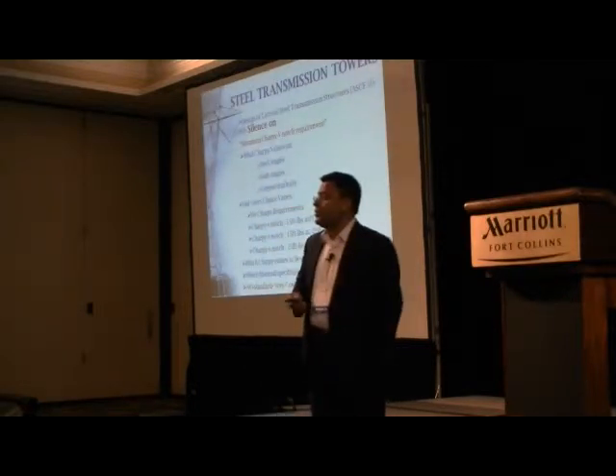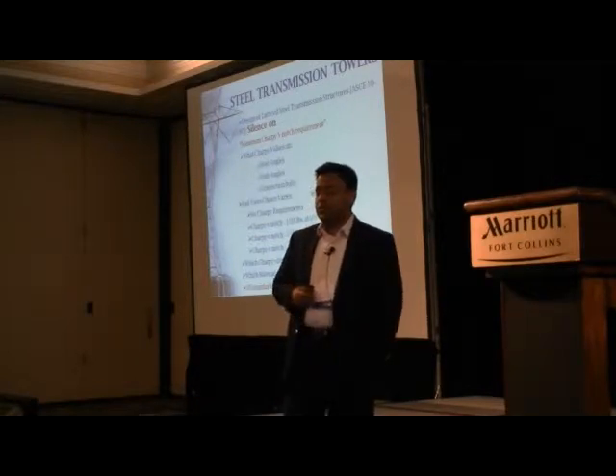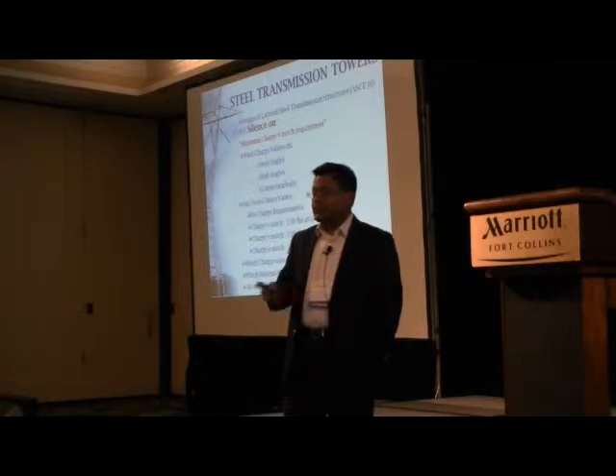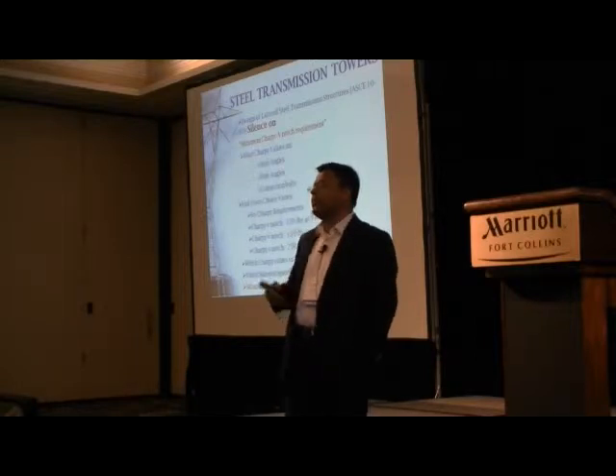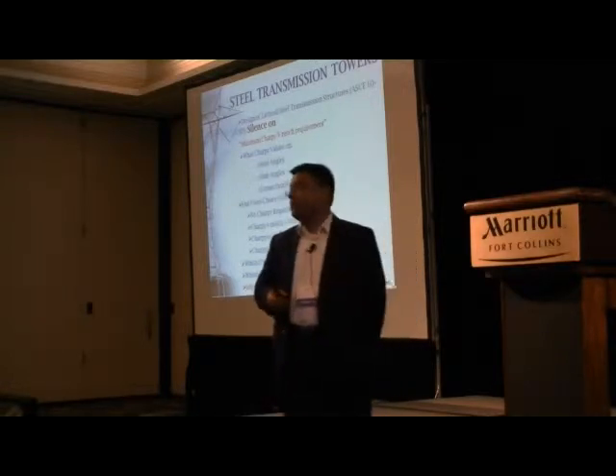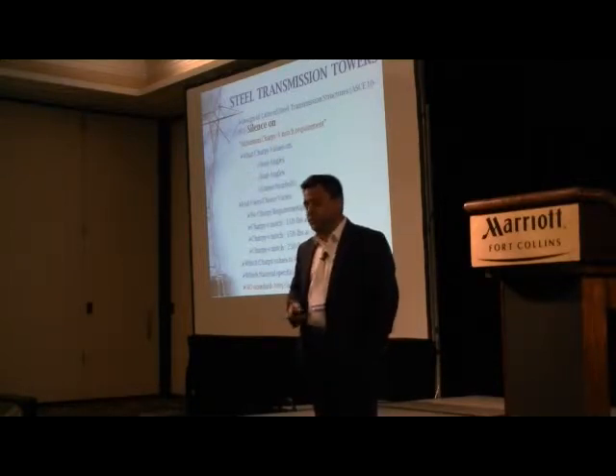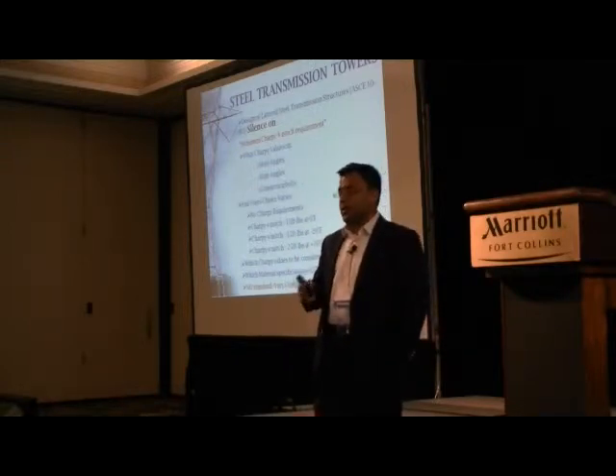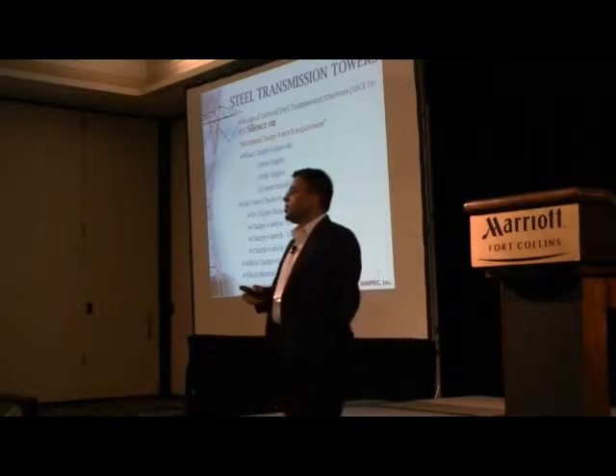When you go to the lattice tower, that standard is silent. What Charpy should we consider? Shall we consider it for the steel, the stub angle, or the connection? There's nothing on that. So now it's more common that people have a choice, and end users decide what Charpy they need. Historically, people would say, I don't need a Charpy. Why? Because I've been using this tower for 30 years, the tower is still standing, so why need a Charpy? Then somebody says, you're right, let's do a number, so I'll choose 15 foot-pound at minus 0 degrees. Or somebody picks 15 foot-pound at minus 20. Somebody goes even more stringent and says 25 foot-pound at plus 10. So what is the real Charpy that we need?